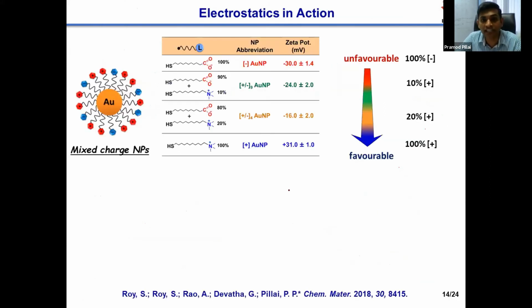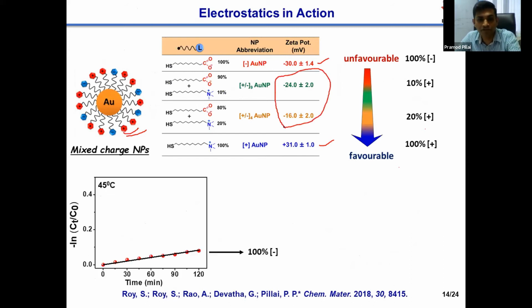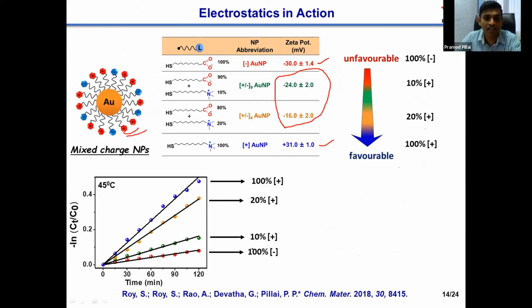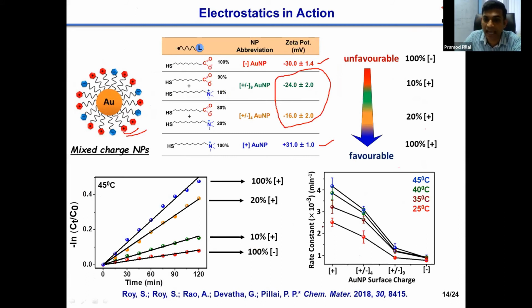And to prove that this is electrostatically driven, we have varied the surface chemistry of the nanoparticle in such a way that we can go from 100% negative charge to 100% positive charge, along with some mixed charge ratio. So what we found is that as we increase the favorable surface chemistry, we are increasing the rate of the reaction. And the important thing is this particular hypothesis is applicable to the different temperature range that we have studied. So the highlight here is that by introducing only 20% of favorable interaction, that is electrostatic attraction, we were able to transform a non-catalyst to a decent catalyst. So this is the strength of surface chemistry that we are trying to bring out in the area of catalysis.